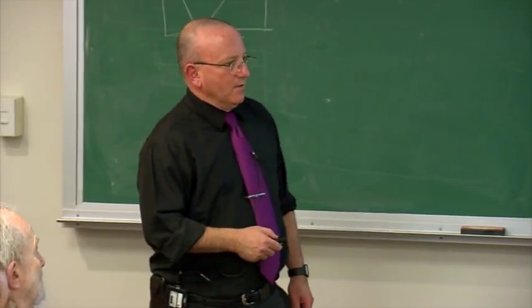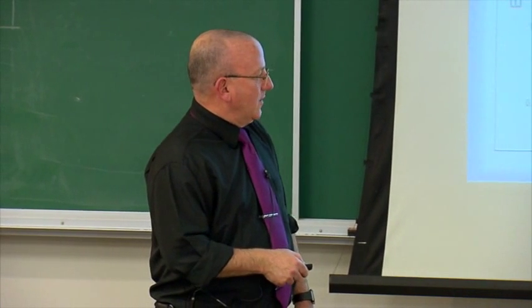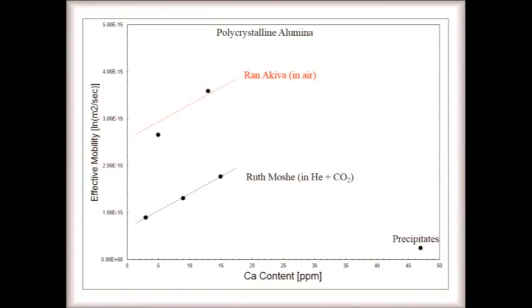By the way, here, Frank, is a sample that was not homogeneous. 51 ppm is a solubility limit. We measured a mean value, which is just under that, but the sample was not homogeneous enough. And this data point is real. In other words, it's growing a lot slower because we have precipitation, which is pinning the grain boundaries. Okay, nothing really surprising, but this is the problem that we have when we don't anneal for a long time.